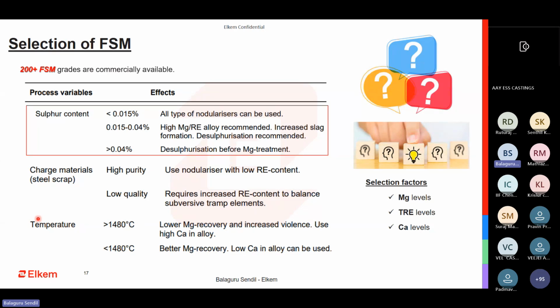So a calm reaction is ideal. To have a calm reaction, the tapping temperature must be low, but unfortunately, due to my layout constraint, or my present process is not good, or I don't have a ladle preheating setup, then I might need a 20-30 degree increase in tapping temperature as a flexibility. So in that case, should I go for a slightly higher calcium alloy? 7% magnesium, 1% rare earth, maybe 2 or 3% calcium, which is going to be beneficial in that situation.